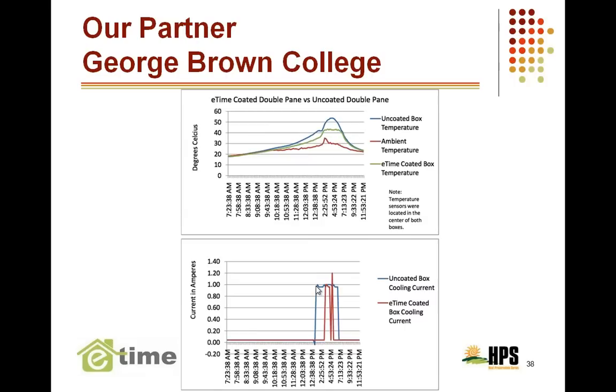Here are the results. We tested on different types of fenestration. This is a double pane clear window, and you'll notice on this that you had a difference of about 11 degrees at the peak point, which is around 3:30, 4 o'clock. That typically happens around the same time of the day. And that's remarkable. It was about 53 degrees on the uncoated box, where the green is the coated with HPS heat shield, and it was 42 degrees, about an 11-degree difference. In Fahrenheit, that would be about a 20-degree difference.